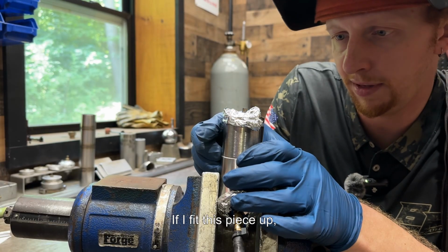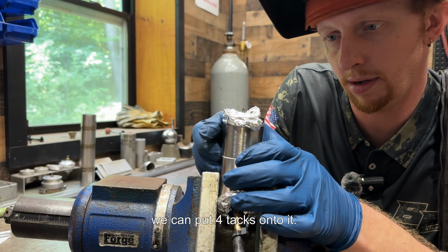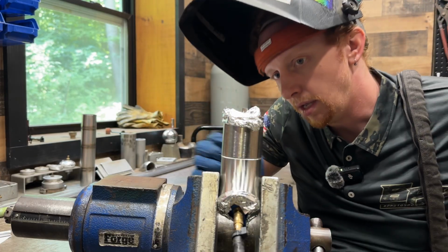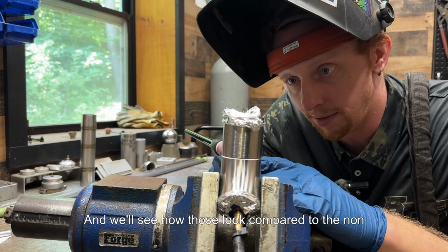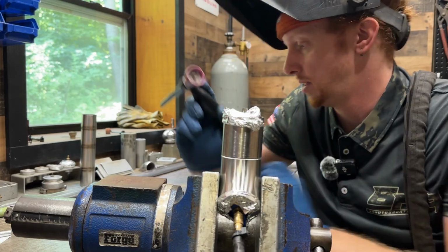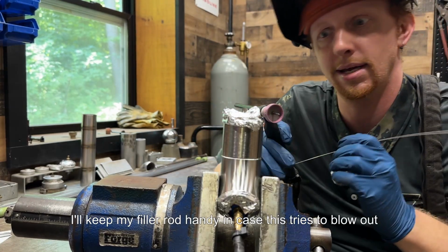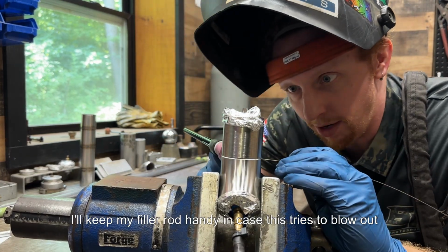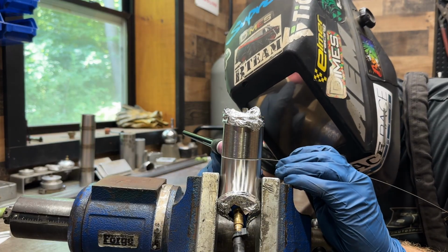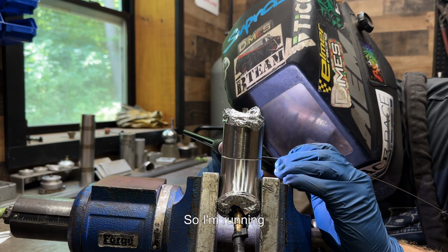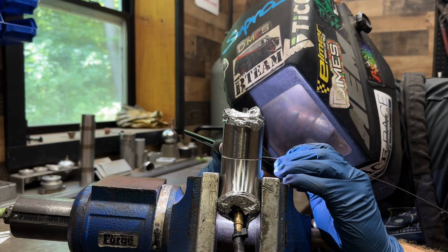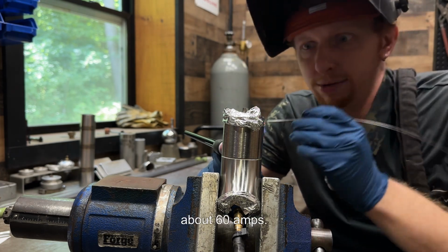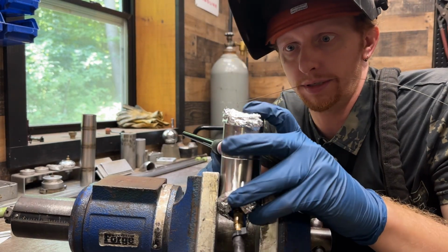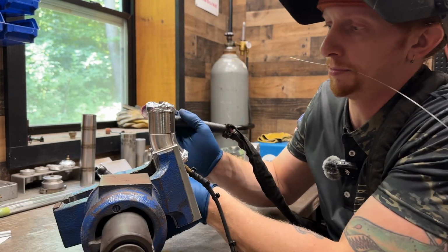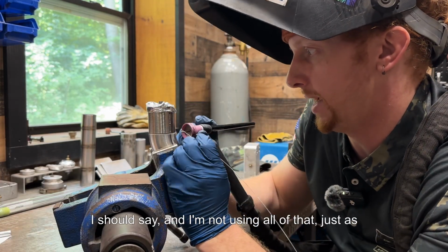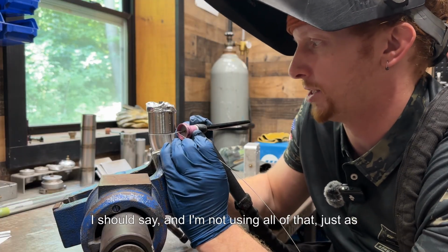If I fit this piece up, we can put 4 tacks onto it. And we'll see how those look compared to the non-purge tacks. So I'll keep my filler rod handy in case this tries to blow out on me. And here we go. So I'm running about 60 amps, or I have the welder set at 60 amps, I should say. I'm not using all of that, just as much as I need.